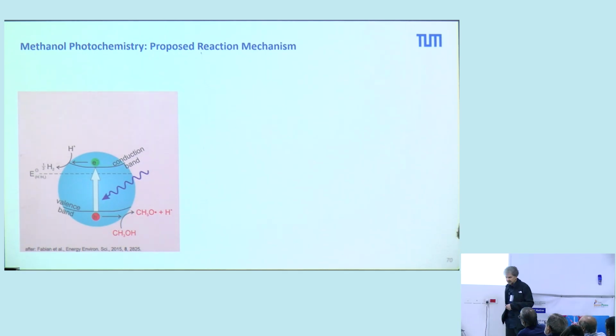If you talk about photocatalysis, 99% of the interpretation relies on this picture here. It's kind of an electrochemical picture. That means you have your semiconductor, you have the upper edge of the valence band, and the lower edge of the conduction band. And in this picture, the redox potentials of oxidation and reduction have to lie within the band gap. That means you have the oxidation at the lower edge of the band gap, and the reduction at the upper edge of the band gap. That means you have restrictions on the semiconductor. You have to align the band gap with the redox potential. And this gives you some limitations.